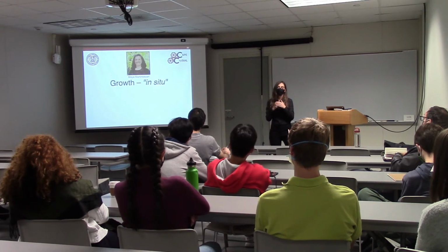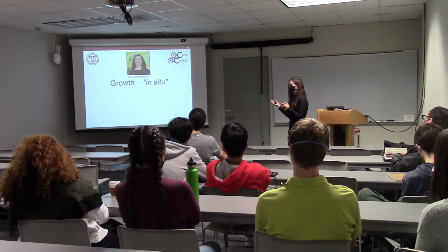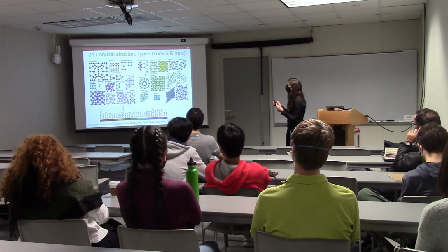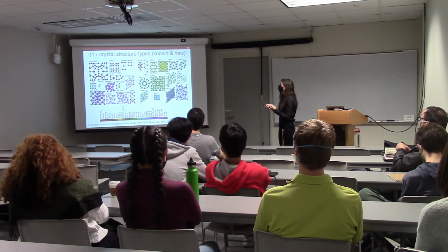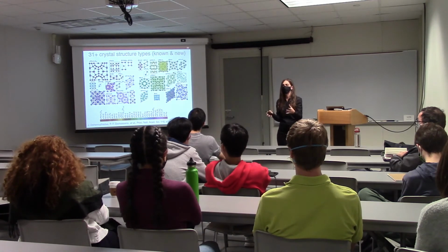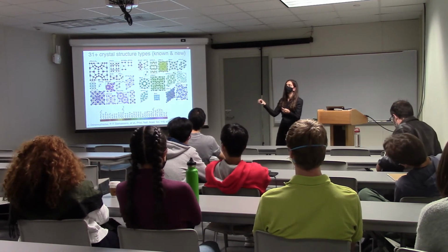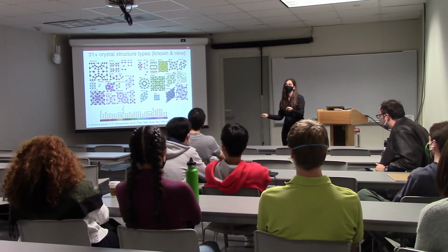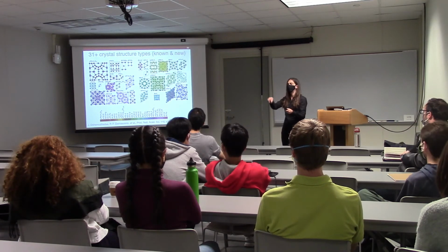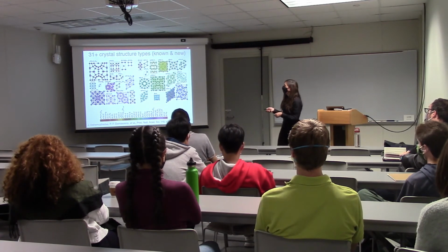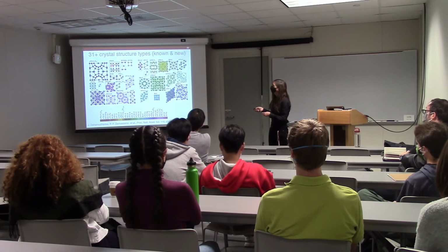So growth is an interesting question here for me. If you think about the complex structures, so let me actually go back 2 slides. Some of these structures are really simple, and they fully fulfill what we think about as crystal growth. We think about crystal growth being one particle coming near a surface and just sitting on its place, and then the next one coming in and replicating the same environment over and over. That's not how most crystals look like, actually. These particles are all identical, but the environments are not the same.